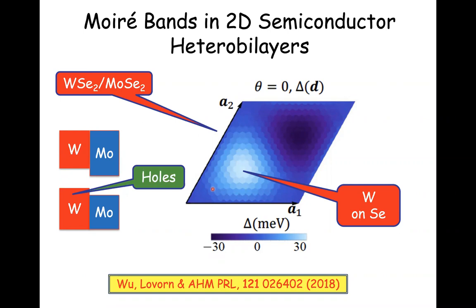So it turns out that in the Moiré structure, you have a model in which you have holes in the valence band with an effective mass that reflects the curvature at the top of the valence band, and they experience a periodic potential with the periodicity of the Moiré pattern. And so this is a very simple artificial crystal.